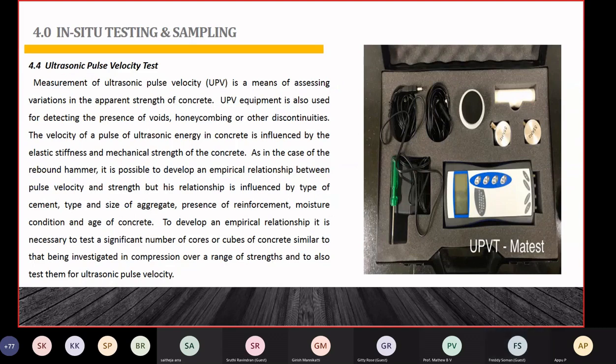It's not a critical issue then. That's why, when we see a crack and want to find out the crack depth also, UPV is the best equipment. Using this ultrasonic pulse velocity equipment, we can correctly find out the crack depth.